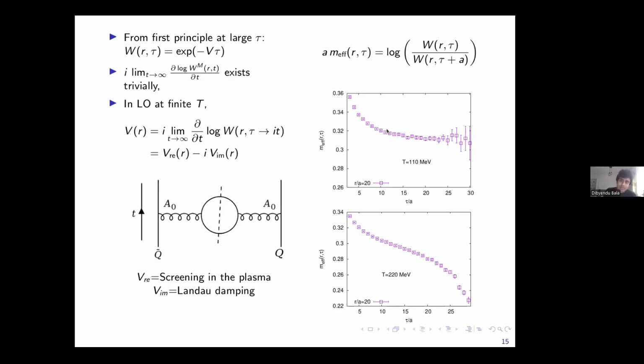Here I show a typical plot of an effective mass from actual lattice data as a function of tau by a. We can see that below around 5 or 10 in lattice units there is no pure exponential decay, but after that it saturates. The fact that it saturates signals a pure exponential behavior. From that saturation value, we can extract the potential at zero temperature. Whenever I say zero temperature, I mean much below the crossover temperature. So it's very easy to calculate this potential on the lattice at zero temperature, because of the pure exponential decay, and I can just analytically continue tau to it and calculate this limit.